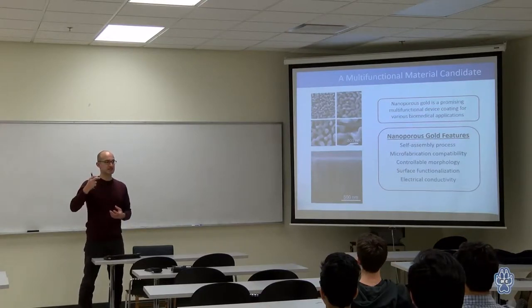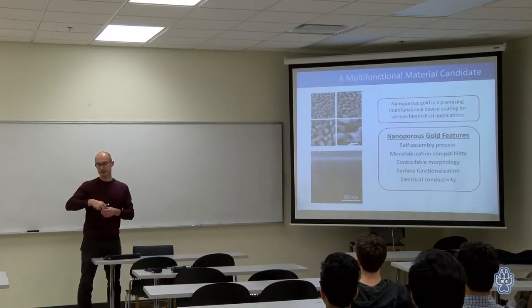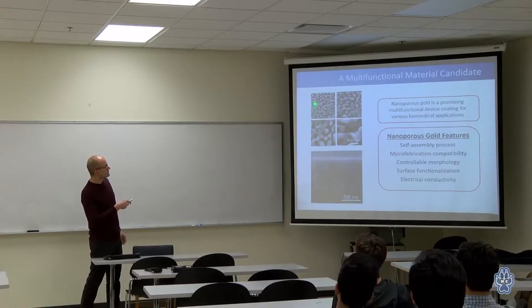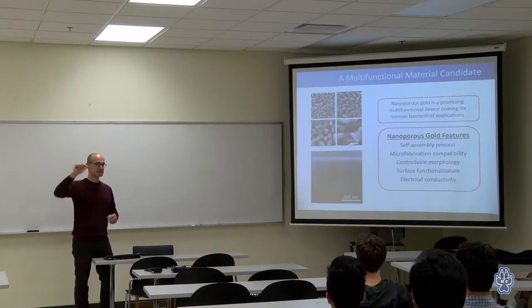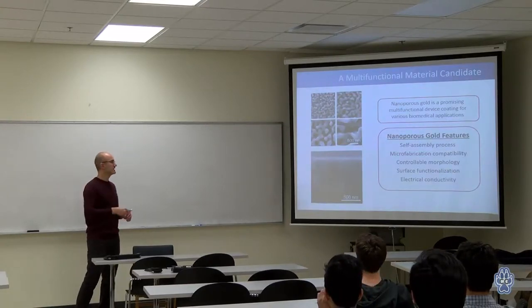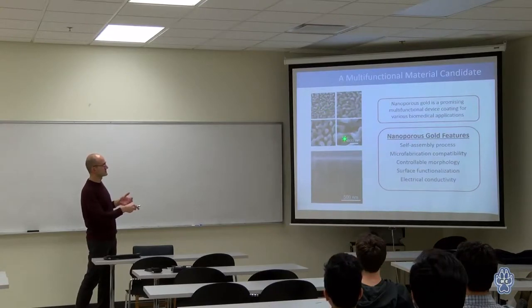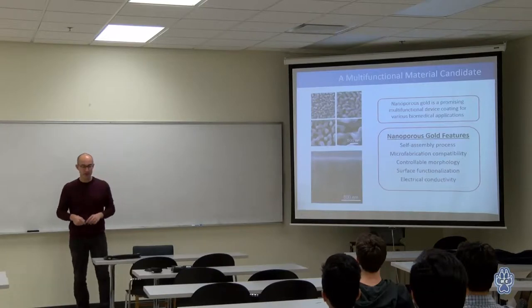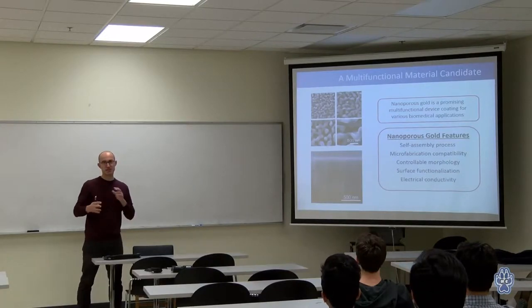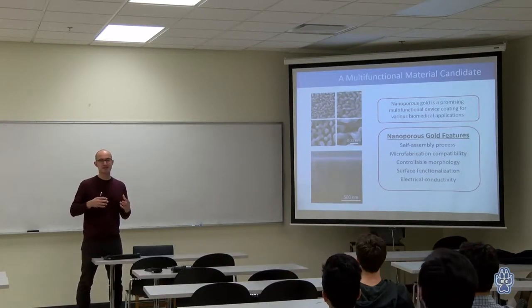Silver atoms are leached. And when the silver is moving away from the surface, gold atoms self-assemble into this porous sponge. So if you heat this up, you basically enhance the atom's diffusion on the surface, and you can coarsen these structures, but keep a similar morphology. So this is important for material science because you can change the structure of the film and study, for example,